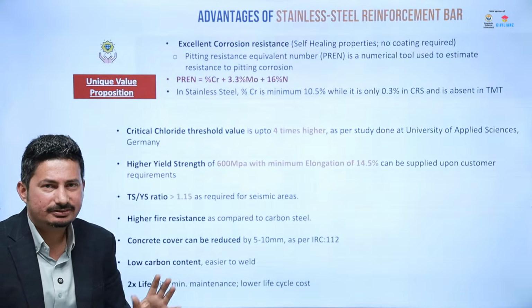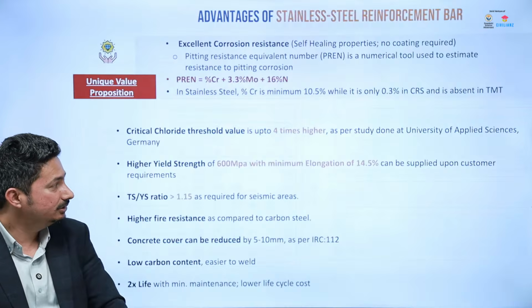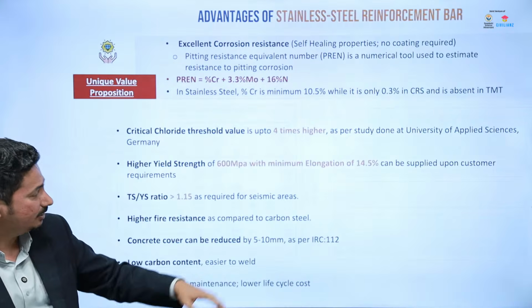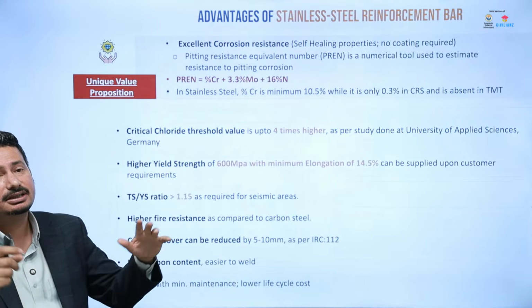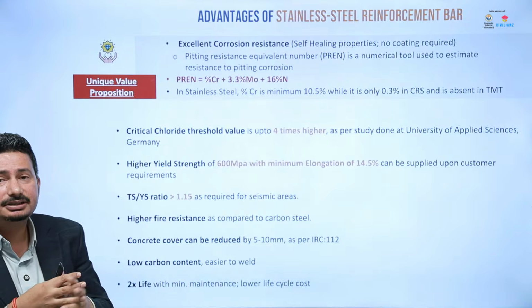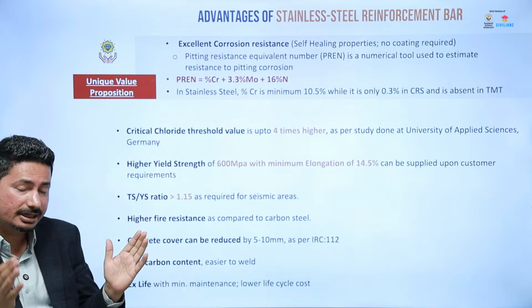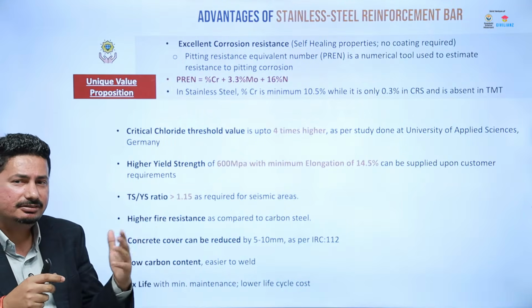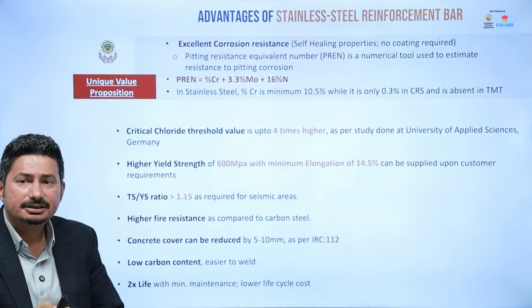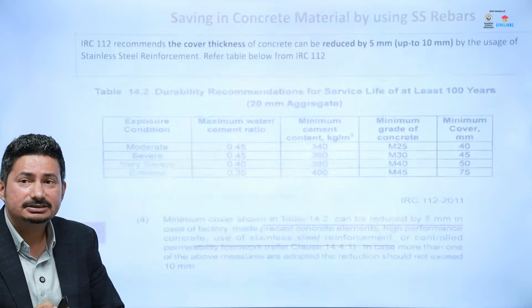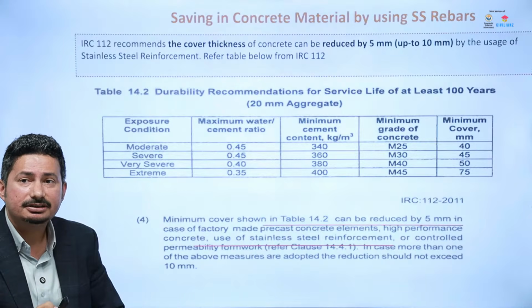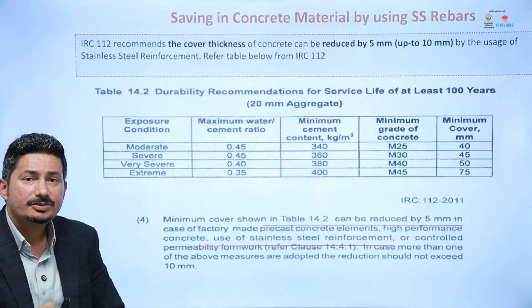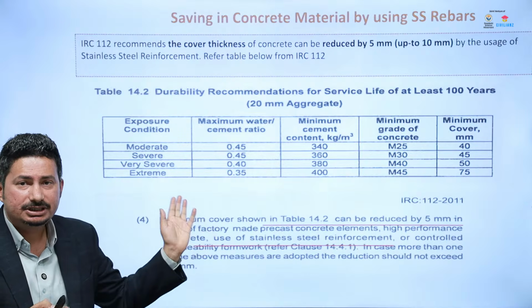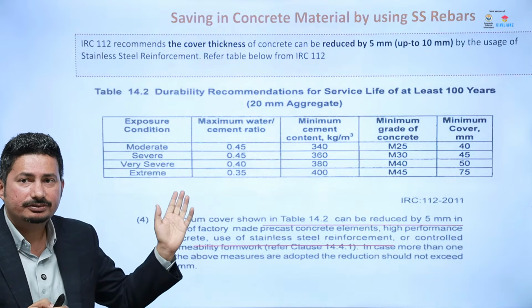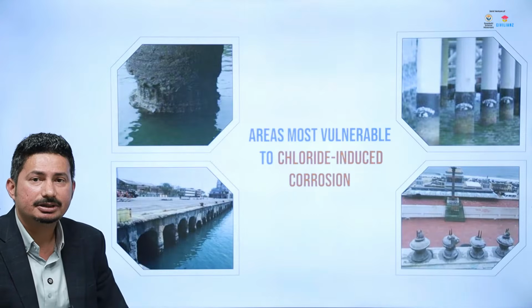Now, there are various benefits of using stainless steel rebars. For example, IRC 112 says we can reduce the concrete cover by 5 mm, and there are various other reasons I have discussed in the slides above. This is IRC 112, which clearly says 5 mm of concrete cover can be reduced if you are going for stainless steel rebar.